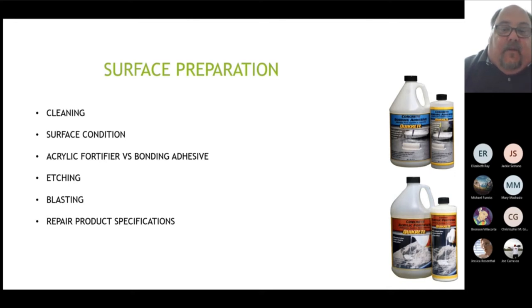Anytime you're etching, if you're going to etch your driveway, say it's so bad with grease and things like that, and you actually want to etch it or use a really powerful cleaner, it's really important to neutralize that at the end. Get a baking soda water slurry, really scrub it in and rinse, rinse, rinse, dilute it. Make sure that it's absolutely free of any kind of chemical, any kind of acid or anything like that, or it's going to affect how this product works, any product works. If you're blasting the floor, your driveway or your sidewalk or whatever, just make sure when you do blast it that you rinse it really well to get any debris out of the pores and the profile of the concrete.